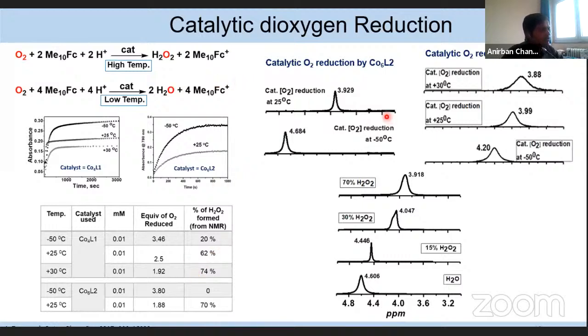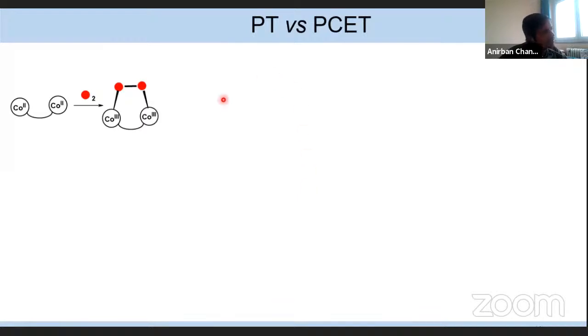So from this UV-vis experiment and the proton NMR study, I came to the conclusion that this catalyst is able to reduce oxygen depending on the temperature. At low temperature, it favors the 4 electron reduction pathway, as you can see from the equivalent of oxygen reduction amount, and at high temperature, it prefers the 2 electron reduction pathway. And it is the cobalt 3 peroxo species, involved in both cases, that controls this 2 electron versus 4 electron reduction pathway. The stability of the cobalt peroxo species is the controlling factor for this 2 electron versus 4 electron reduction pathway.